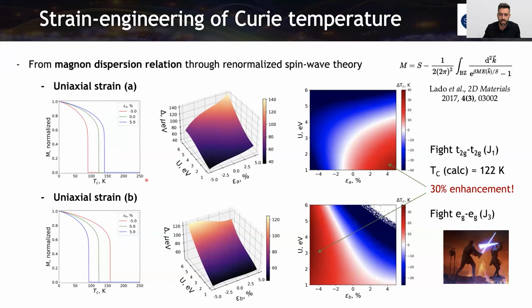And then we are applying the strain to evaluate two things here, the magnon gap and the Curie temperature. In the case of the magnon gap, we can observe that it's increasing when we are applying strain along the A-axis and also increasing the Hubbard-U. But this is not translated here into an increase in the Curie temperature, because in this part of the spectra, the interactions are favoring the antiferromagnetic mechanism.